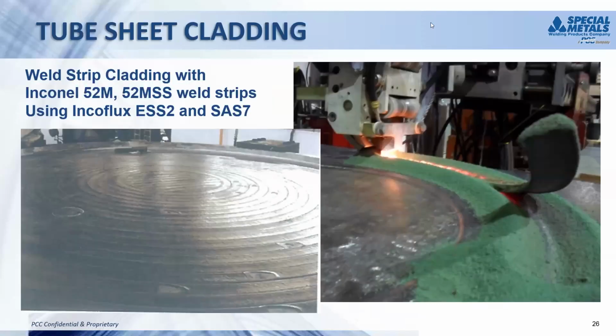Along in those same alloy groups, you've got a lot of components that were entirely clad with the 52M and the Inconel 52MSS, done with multiple processes. One of the most efficient we'll talk about here is with weld strip. With weld strip, instead of a single point, which you would have with a wire, you've got a much wider strip, so you're covering a lot more area of a component. That's a big advantage as far as a time saver.